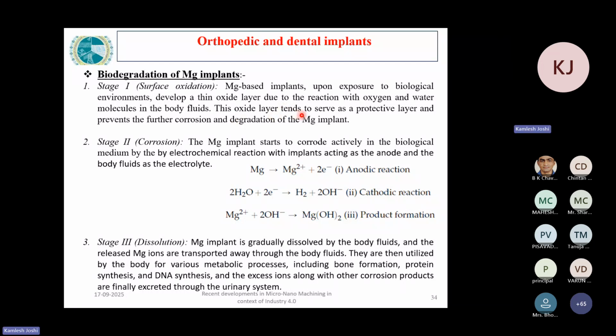And these oxide layers tend to serve as a protective layer and prevent further corrosion and degradation of the magnesium implant. In the second stage, the corrosion starts. The magnesium implants start to corrode actively in the biological medium by electrochemical reaction. So the anodic and cathodic reactions are shown here. Magnesium first